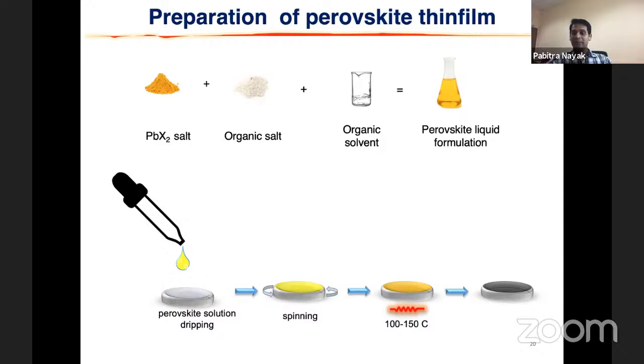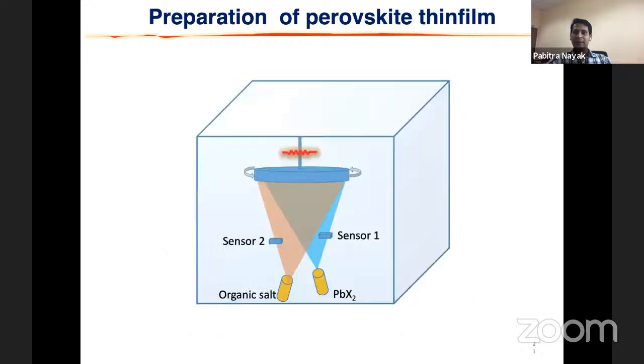Now, how do you prepare the perovskite in other ways? Well, you can put it in a box and take the air out, so you create a vacuum. Then you put in organic salt and lead salt. You just heat it. When they come and land on the heated substrate, they'll form the perovskite. So this is another way of making perovskite thin films. And you can control the thickness the way you want, right?